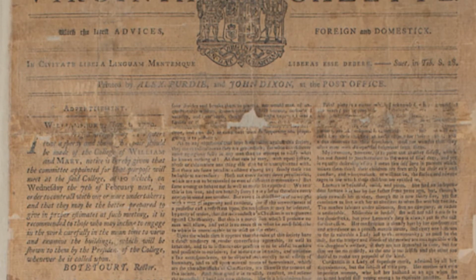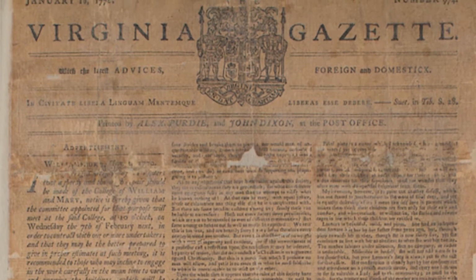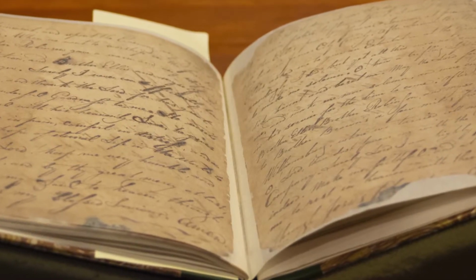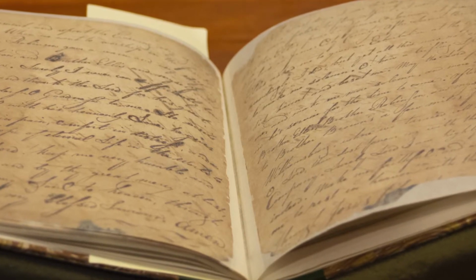What happens over time is that the plastic, cellulose acetate, breaks down, and one of the components of that deterioration of the plastic is acetic acid. There's a symptom of degrading laminated documents called vinegar syndrome. And the odor of vinegar is, in fact, that off-gassing of acetic acid. The result is something that looks very unnatural. The integrity of the paper is altered by the lamination process.